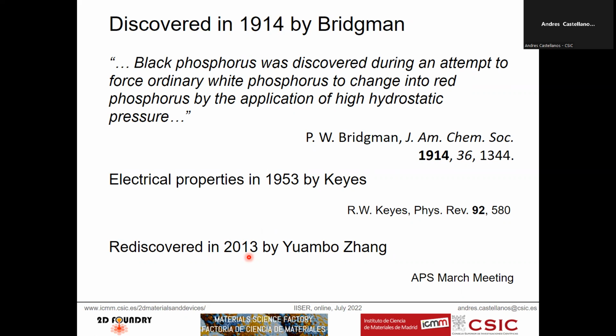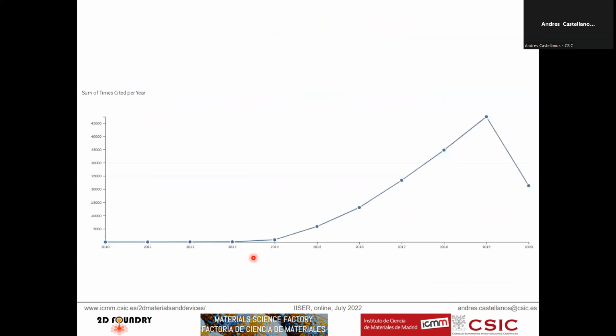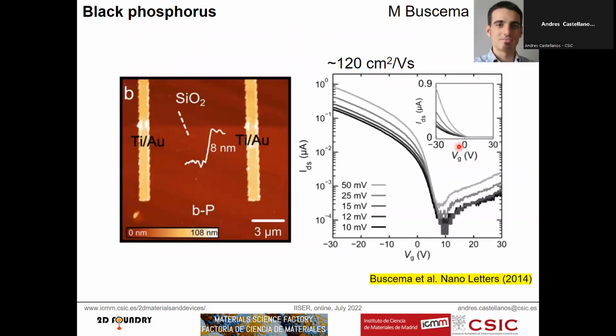From 2004, plenty of people isolated other two-dimensional materials, but all of them were compounds: molybdenum disulfide, niobium diselenide, high temperature superconductors like BSCCO, mica, all different compounds that have complex chemical structures. And black phosphorus is the first single element two-dimensional material beyond graphene that was isolated, and it opened the door to more mono-element two-dimensional materials. Yuambo Zhang's talk was in 2013, the first papers came out in 2014, and the field is growing like hell. It's one of these research fields that is very active.